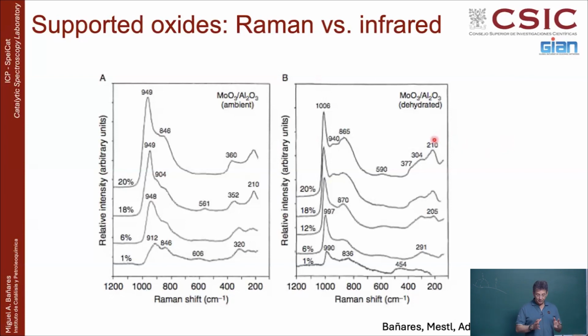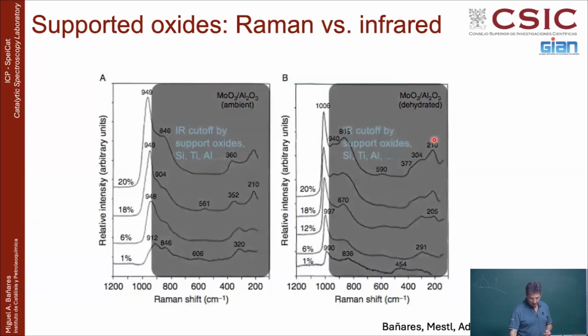Now, you can get a lot of information if you are making Raman spectra of these materials, particularly under dehydrated conditions. And I didn't say, but all the infrared spectra I showed you before are dehydrated, because we have always made them dehydrated. Why? Because water is a problem, CO2 is a problem, so I make a vacuum treatment and we make it in situ in my cell without humidity, without CO2, without many things. So infrared has always been working with in situ dehydrated samples, to the point that people were not aware how important that was. But that was good. Getting rid of the water and CO2 was very nice, mainly water, because water has a dramatic effect on the structure of the materials. Okay, but this is something that we will see later on about Raman.